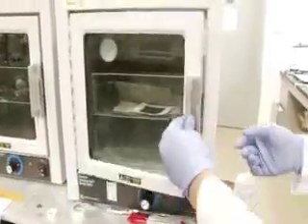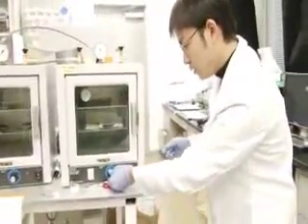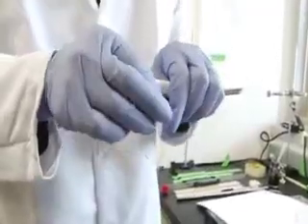You can dip it in, you can just print it. Paper is a highly polar structure. So once you have that paper with ink, you put it into an oven, you bake all the water out, then you have a really conducting paper. Going from initially a well-insulating piece of white colored paper, it becomes black carbon nanotubes — highly conducting paper.